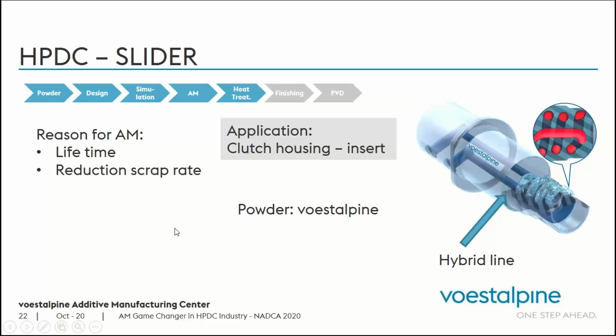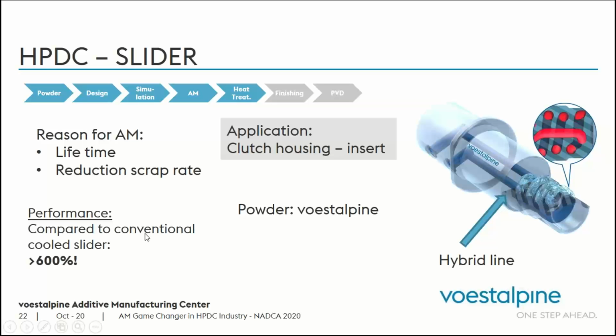And the reason to use AM here, what we usually need to identify before working on a project, is what is the value? Why do you want to apply additive manufacturing? So this was a reduction of scrap rate with a target on lifetime as well. So what we were able to get on the performance, compared to a conventional cooled slider, 600% improvement. In this case, from 8,000 parts that you were able to get from conventional design, we are able to get 50,000 parts. That's an unbelievable improvement that you can get by additive manufacturing, from 8,000 parts to 50,000 parts. It's an unbelievable achievement that you can get by redesigning the part inserts by additive manufacturing.